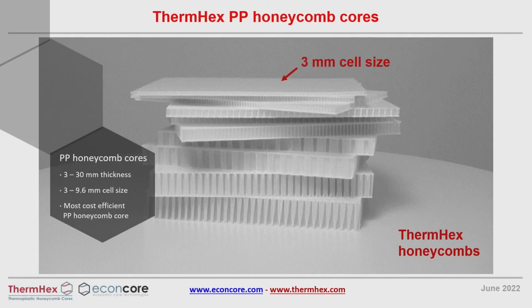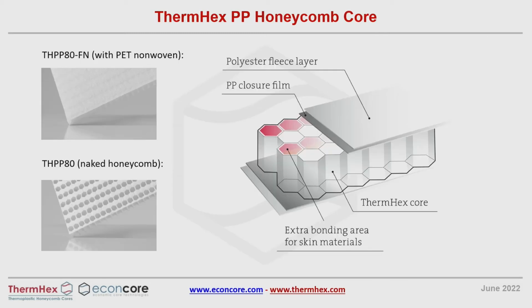So with this we can produce a honeycomb core with very small cell sizes and in thicknesses from 3 to 30 millimeter. So we have special skin elements to bond the skin due to our production process, and this allows a very reliable core skin bond.